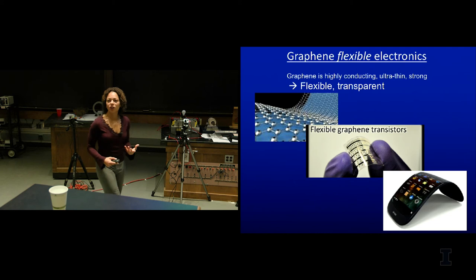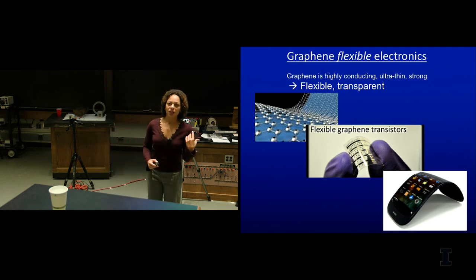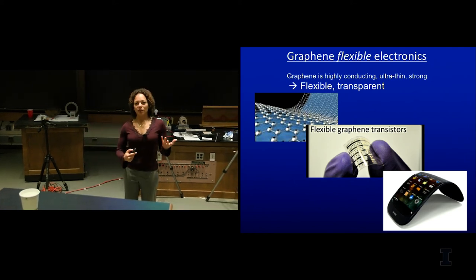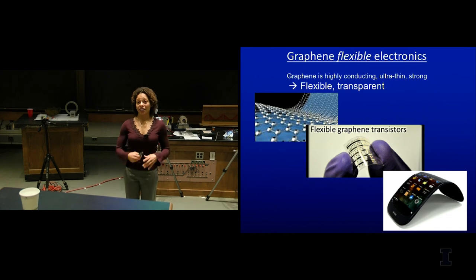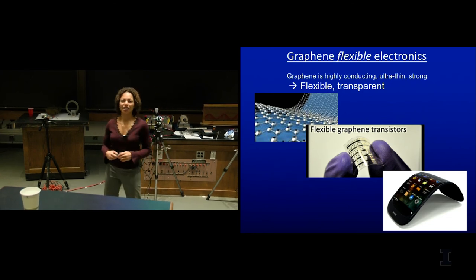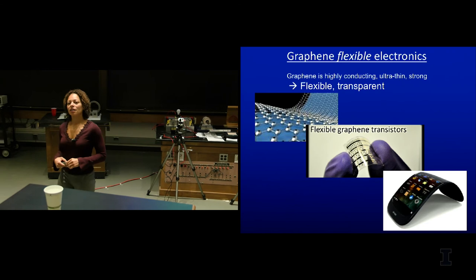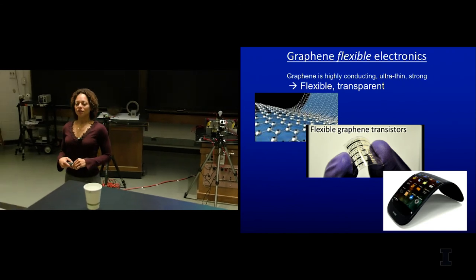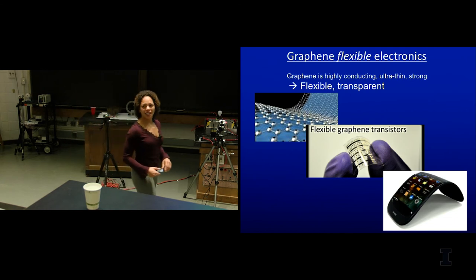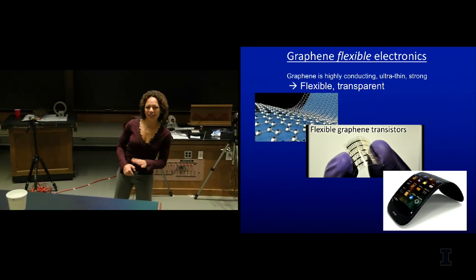As you cool it, it's also very robust. So in our lab, we cool it to a few degrees above absolute zero, and then it just gets really interesting electronically, but it doesn't change its properties very much. Superconductivity, this is not, but we do a lot of that in my lab, and I could tell you about that another time, but this one does not happen to be.